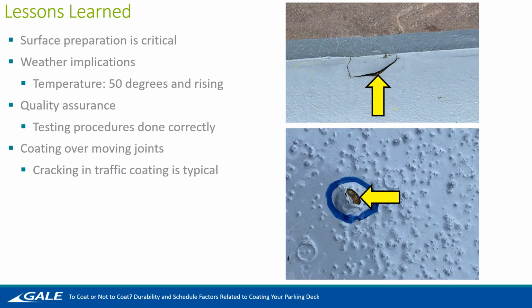In the photo on the top right, you can see that the traffic coating failed shortly after it was fully cured. And it didn't fail at the concrete, it failed at the base layer because it wasn't properly cleaned. So the adhesion between all the layers is really critical with the surface prep as well. Now, what are the temperature implications? Most traffic coating products say 50 degrees and rising, but we found that sometimes if you install at 8 a.m. and it's 50 degrees, but it's going to heat up to 70 degrees during your cure time, your traffic coating is not going to cure evenly. It could come with bubbles and a bunch of other defects that you're going to have to fix.